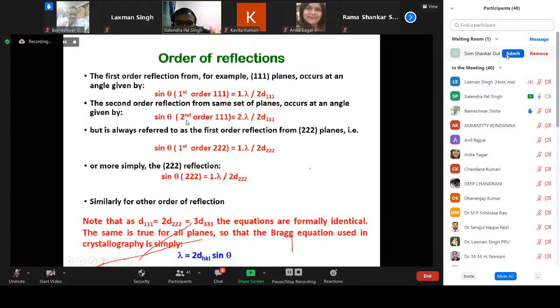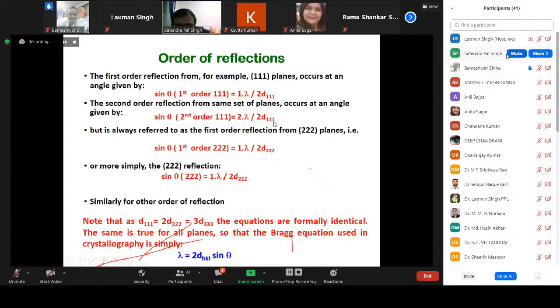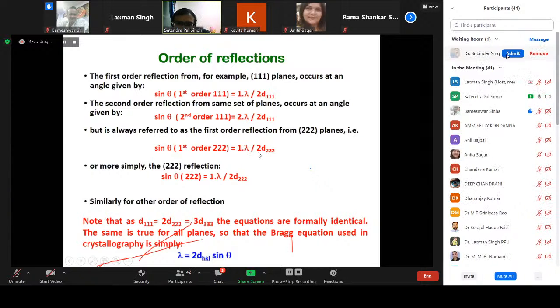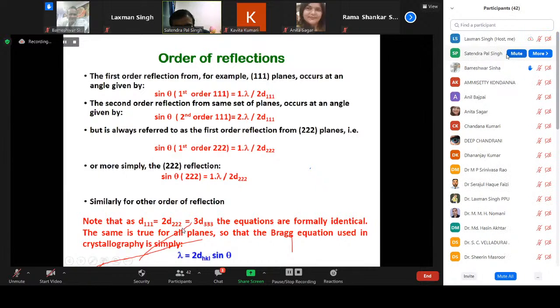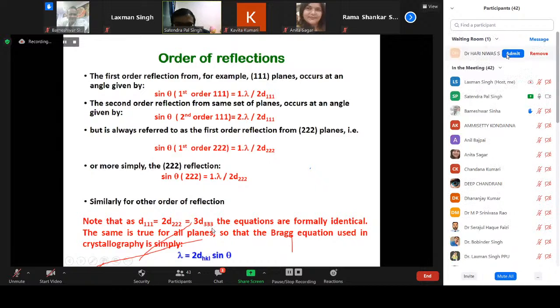The second order reflection from 1, 1, 1, with n equal to 2, gives sin theta equals 2 lambda over 2 d 1, 1, 1. This is similar to the first order reflection from the d 2, 2, 2 planes. Similarly, the 3, 3, 3 reflection can be a third order reflection from 1, 1, 1, or a first order reflection from d 3, 3, 3. So we know that d 1, 1, 1 is equal to 2 d 2, 2, 2, which is equal to 3 d 3, 3, 3. The equations are almost the same.